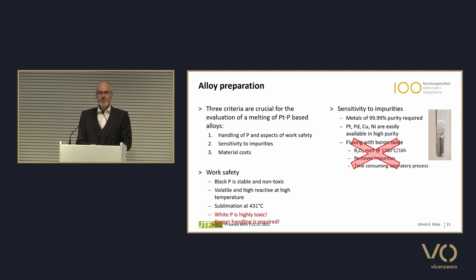What is also important, I mentioned impurities, so you can work with high purity raw material, no problem usually with precious metals, but often in laboratory or in scientific literature it's described that you need to flux these alloys. So fluxing means you put the alloy, the cast part, and cover it with boron oxide. Then you melt the boron oxide, and you boil it at 1200 degrees for 16 hours, so quite a long and time-consuming and energy-consuming process. And of course, working with boron oxide is also not nice. It's also not very healthy. And we wanted to avoid this process because we think it's not practical if someone wants to produce these alloys.